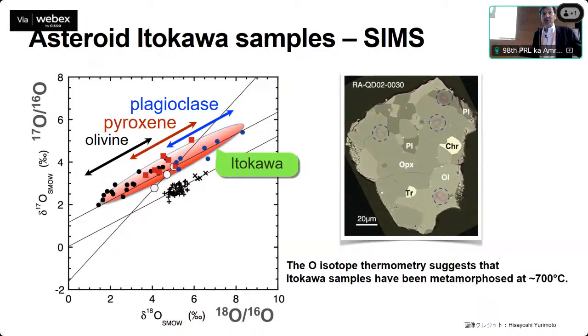So this sample was metamorphosed at 700 degrees in the parent body. And in order to reach 700 degrees, the parent body size should be bigger than 100 kilometers. So we can infer the parent body size from this analysis.